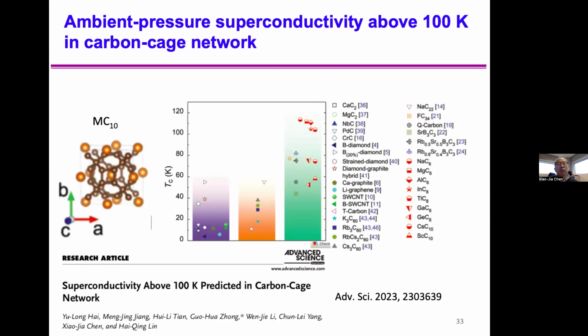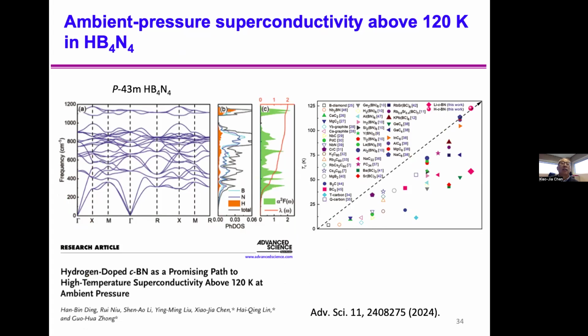Following this way, we were also thinking about the cage in the hydride. We borrow this idea also for light elements. The light element is carbon. It's a carbon cage network. We chose a lot of systems. We found that TC, even at ambient pressure, can hold a transition temperature above 100 Kelvin. That's in a carbon cage, also a light element. Here is a boron nitride, BN4. When you form a compound with hydrogen, we call it hydrogen boron 4 N4. This material also has a TC around 120 Kelvin at ambient pressure.